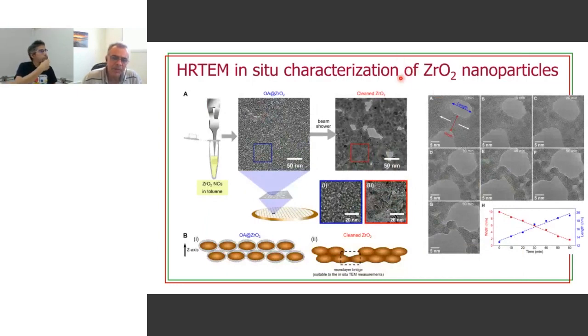Okay. The first part is to produce zirconia nanoparticles. We have a sequence of steps that, of course, as a theorist, I have very limited knowledge about, but I may be able to just explain the very basics. We form some zirconia nanoparticles in solution, and you encapsulate these zirconia nanoparticles with some organic compounds. These are oleic acid in our case, and you take this to the microscope grid, right?